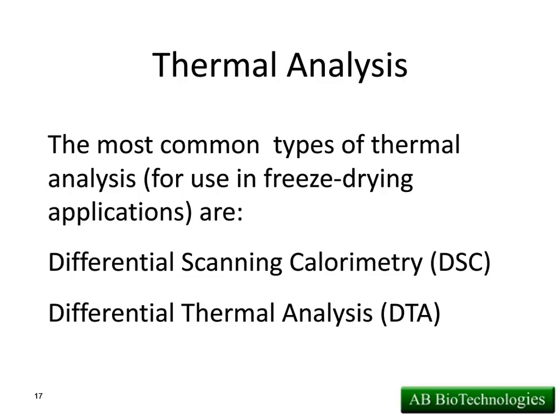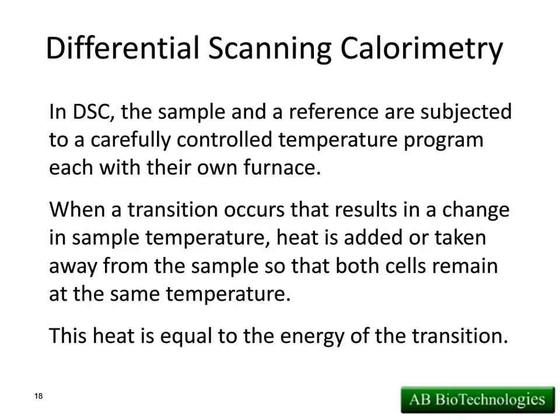Now, the differential thermal analysis system is older technology. It does give you some limited information, but the DSC is what we use in our lab and what most companies are using if they're doing thermal characterization. Basically, in DSC, we're taking our sample. The sample is going to be in its liquid state, and it should be representative of the formulation, meaning it should be the same exact formulation sample that you would put in a vial and add to your freeze dryer.